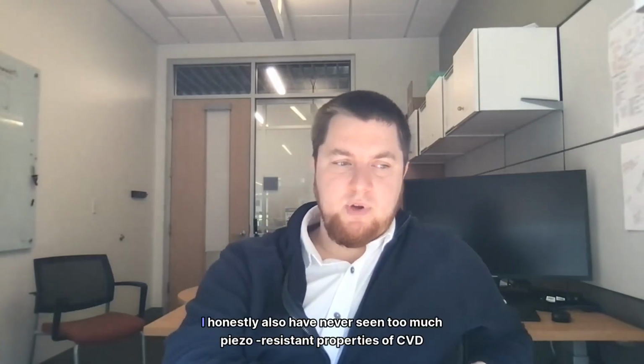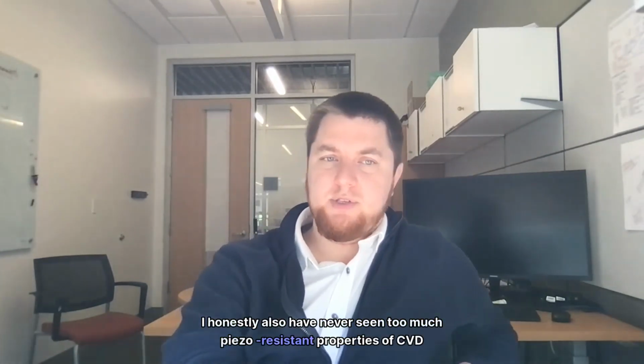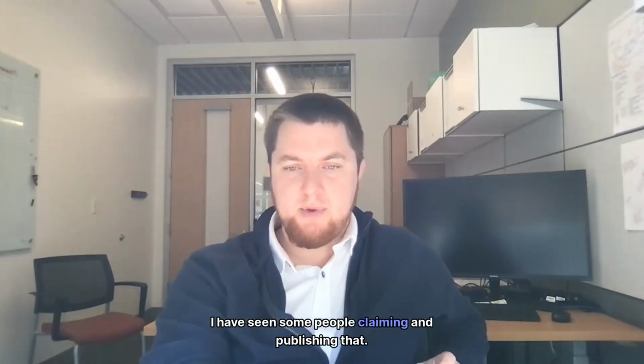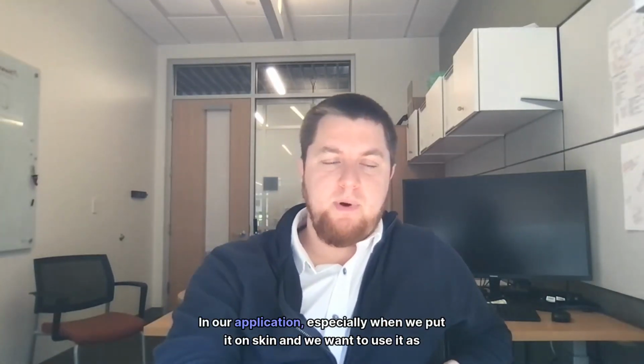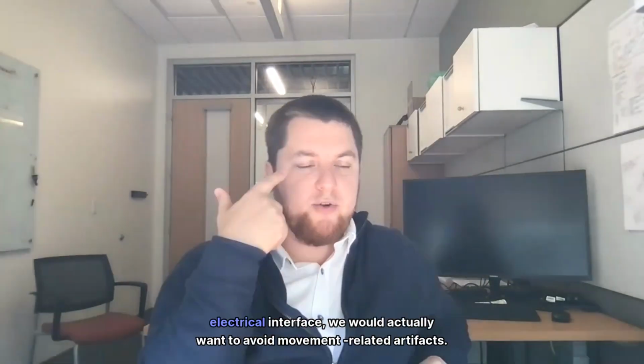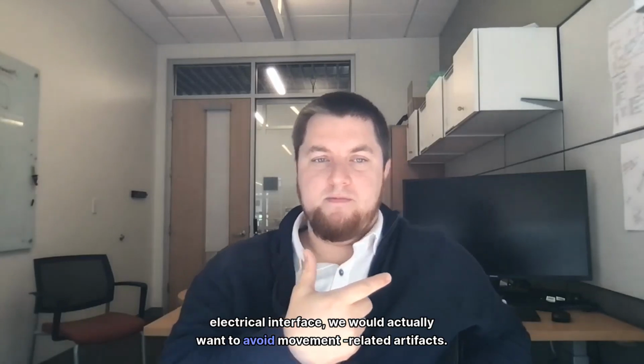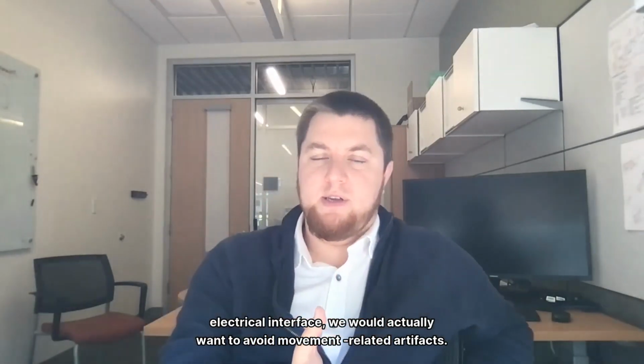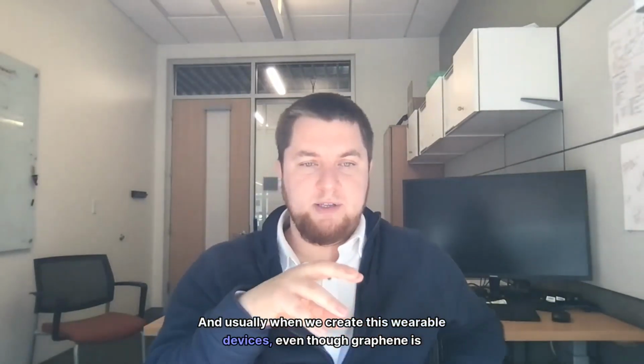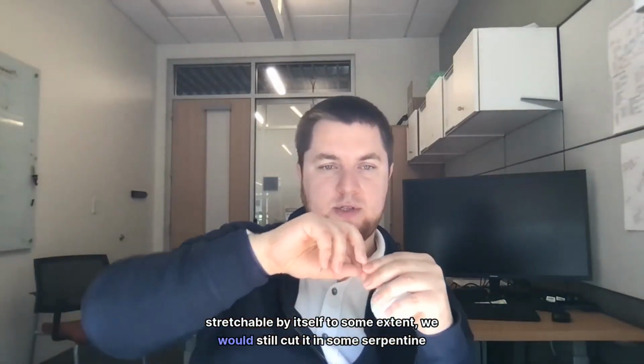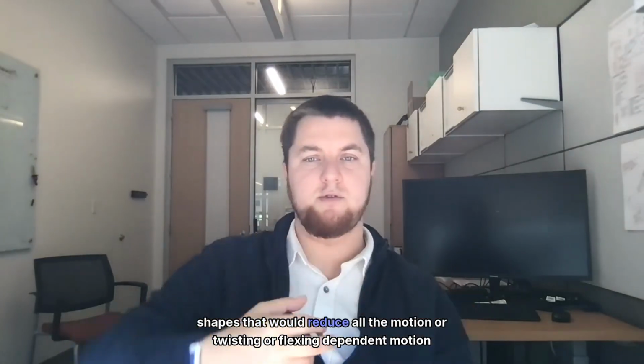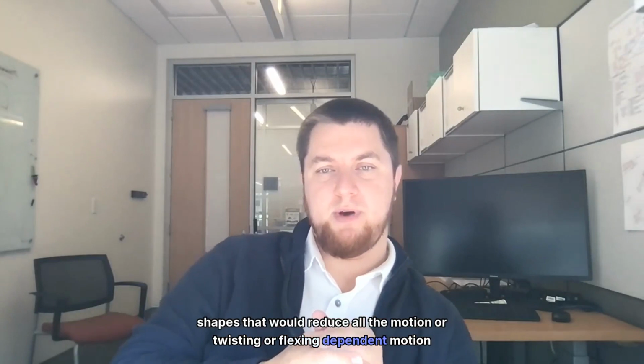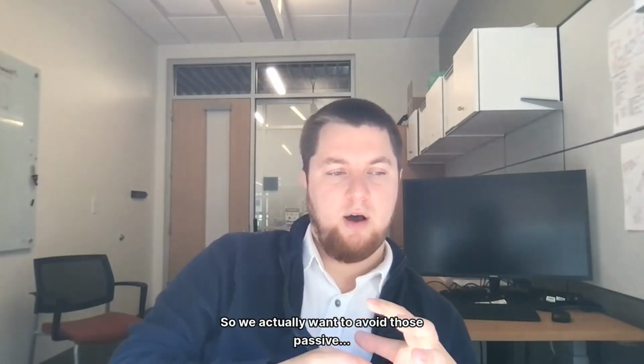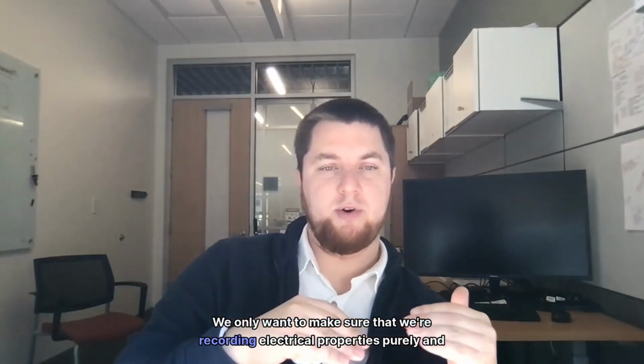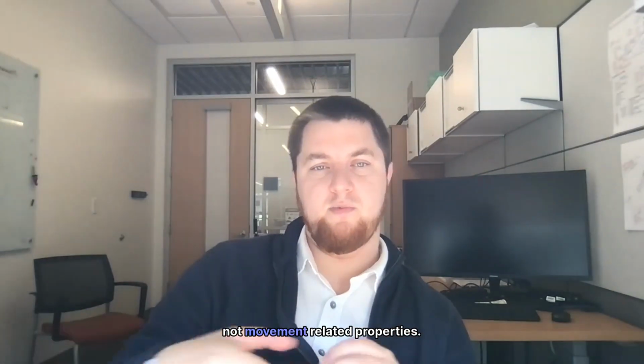I would say not. I honestly have never seen too much piezoresistive properties of CVD graphene. I have seen some people claiming and publishing that. In our application, especially when we put it on skin, right, and if we want to use it as an electrical interface, we would actually want to avoid movement-related artifacts. And usually when we create these wearable devices, even though graphene is stretchable by itself to some extent, we would still cut it in some serpentine shapes that would reduce all the motion or twisting or flexing dependent motion artifacts. So we actually want to avoid those passive signals that could come from movement. We only want to make sure that we're recording electrical properties purely and not movement related properties.